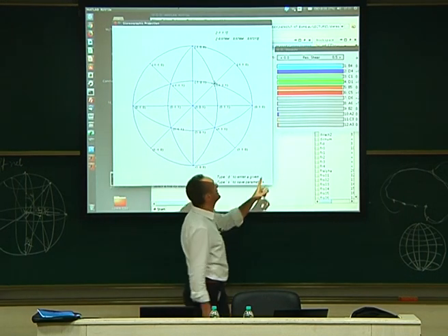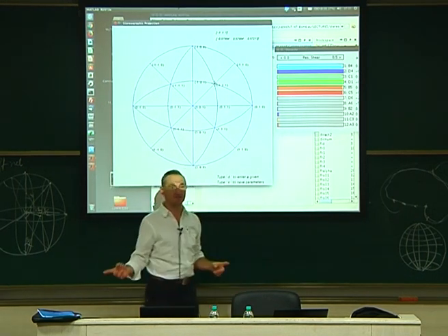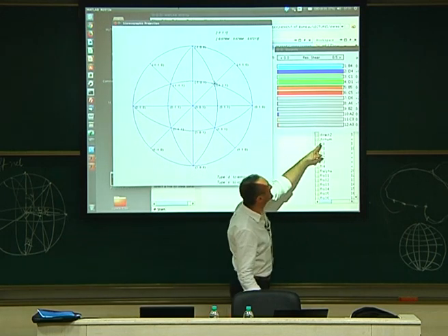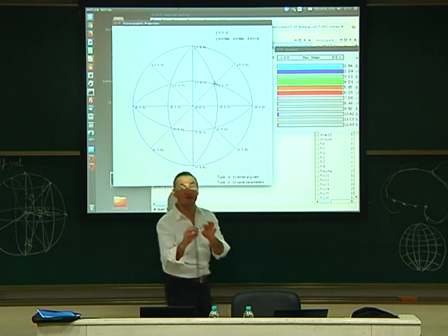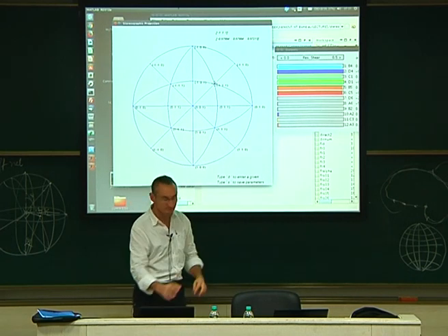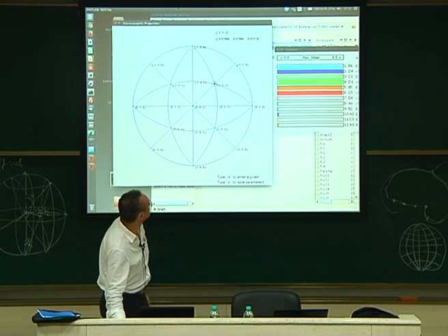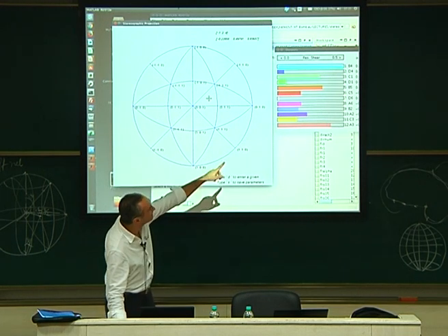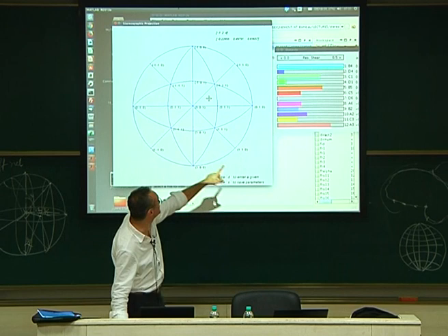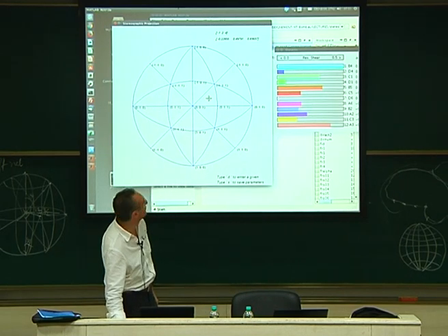What is nice with that symmetry, what we call a high order symmetry, is that the remaining 6 have 0. They are exactly 0. They are not a little bit loaded, they are not loaded at all. Now if you go in the standard triangle here, you see that here you are in pure shear on B4. So this is typically B4 orientations.